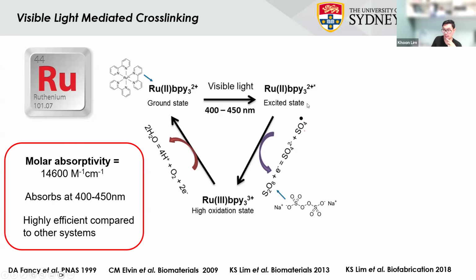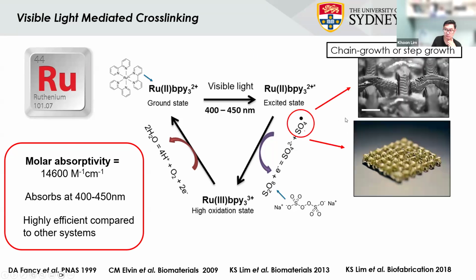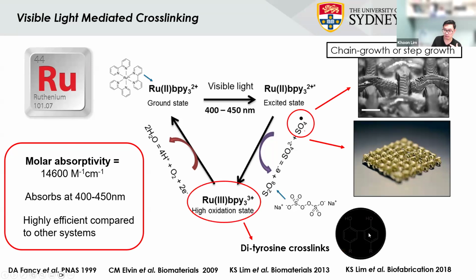You can make gels in the presence of an electron acceptor. In this case, we often use sodium persulfate. You can form these sulfate radicals, and these radicals then can propagate to start different chemistry. So chain growth, step growth, or even dityrosine crosslinks. In this case, I'm sorry you can't see, but this is two biphenyl bonds, biphenyl bond here.